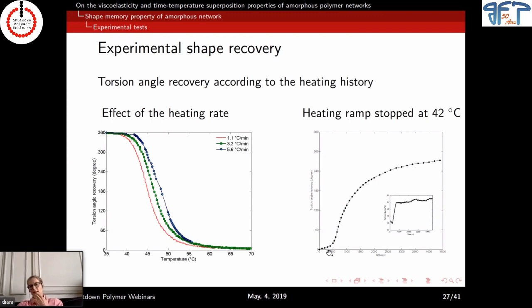rate. We also applied a heating ramp of 1.1 degree per minute until reaching 42 degrees and tried to keep it at 42 degrees and look at the recovery over time.